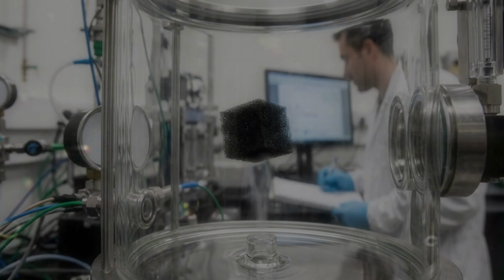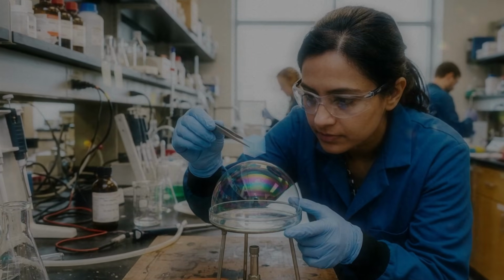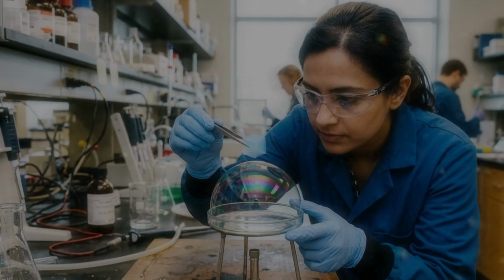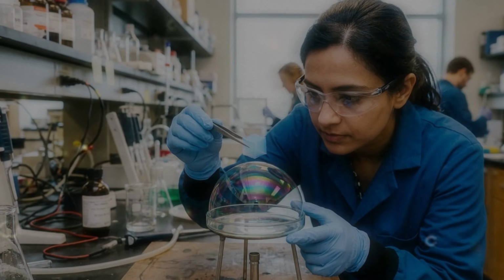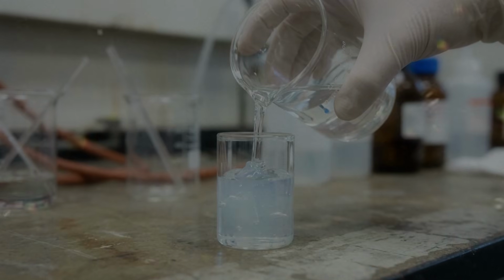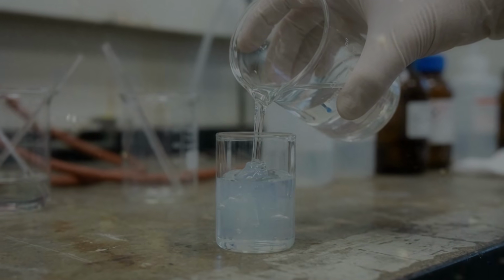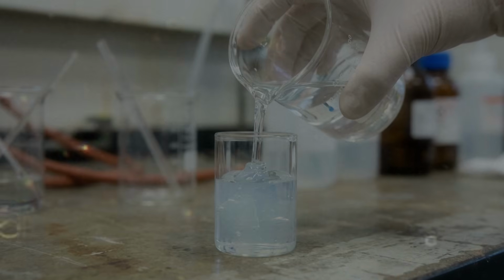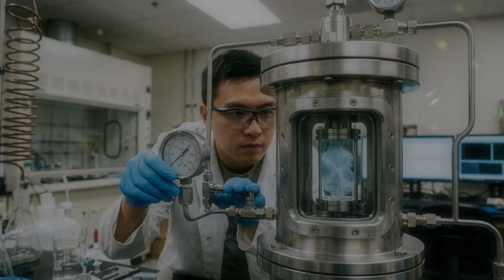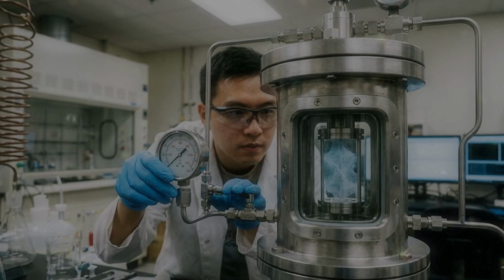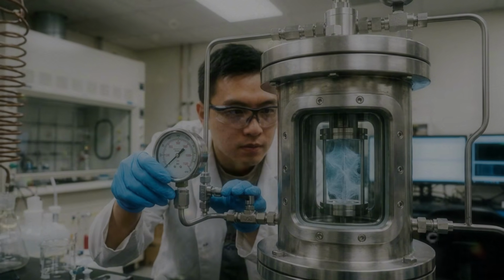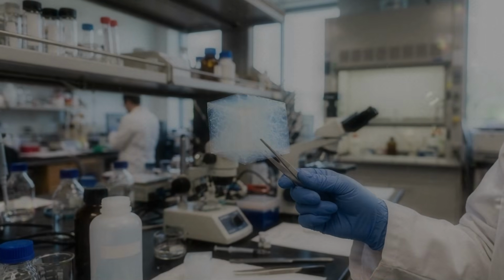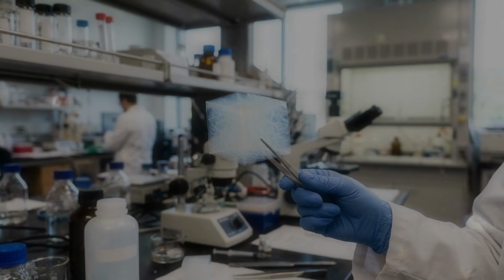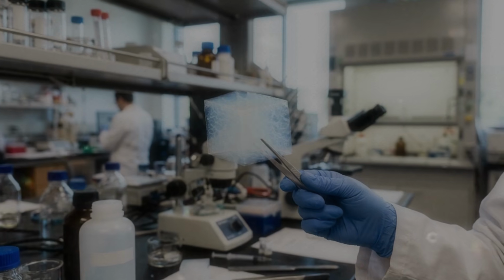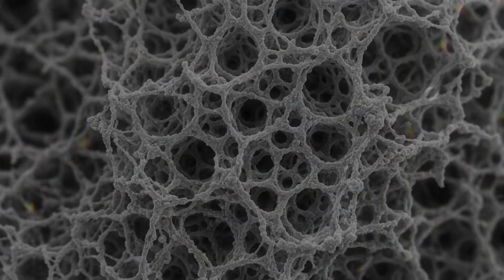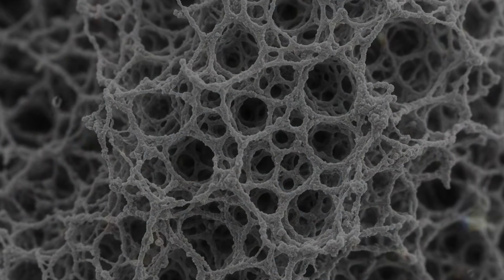Every addition changes more than one property. A polymer may increase strength but reduce heat resistance. A metal particle may improve energy storage but add weight. A water-repelling treatment may protect the material from moisture but reduce its ability to interact with certain liquids. Material design therefore becomes an exercise in choosing which compromises are acceptable. The lighter sample is not always the best sample. The strongest is not always the most conductive. The greatest surface area is not always the easiest to use.